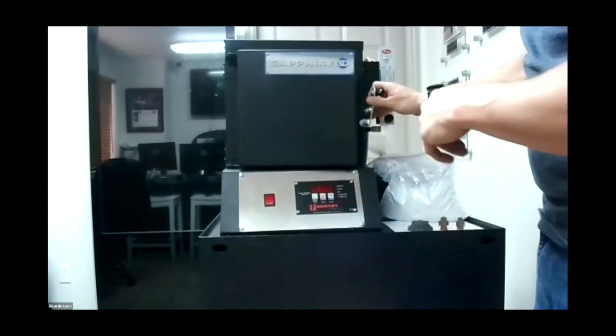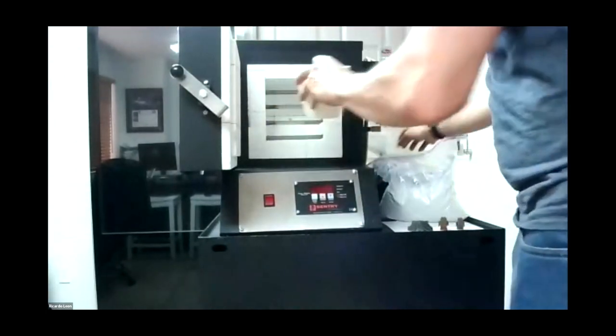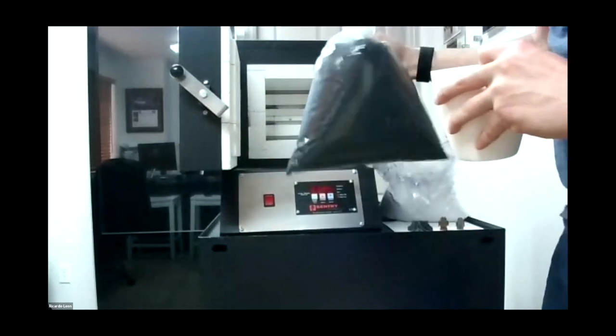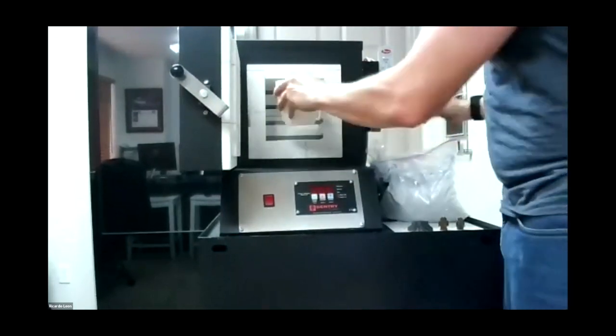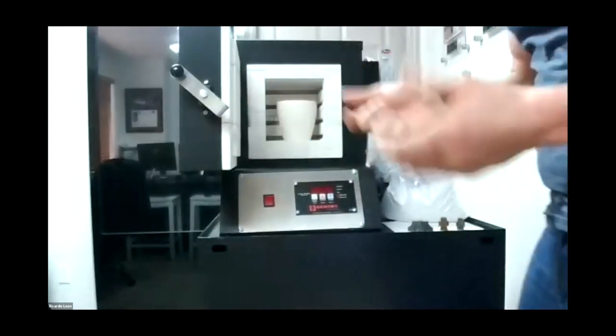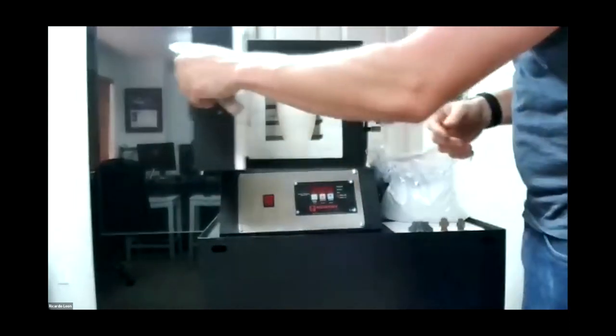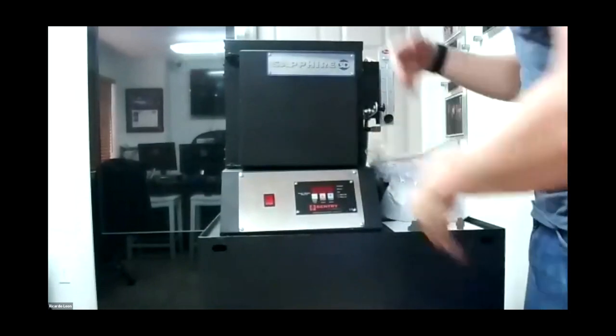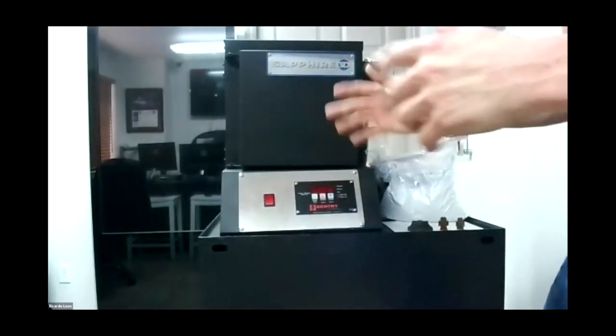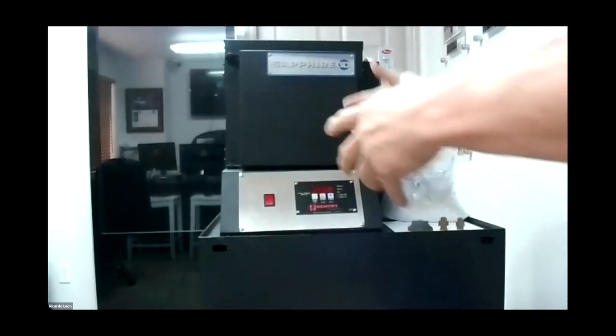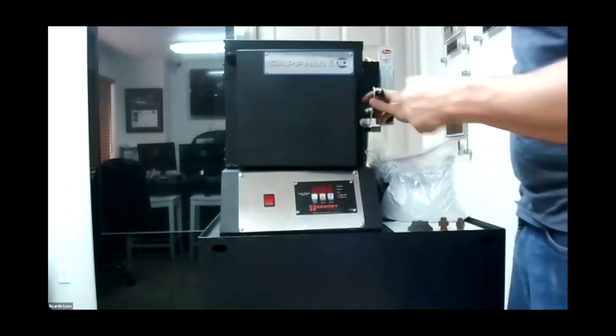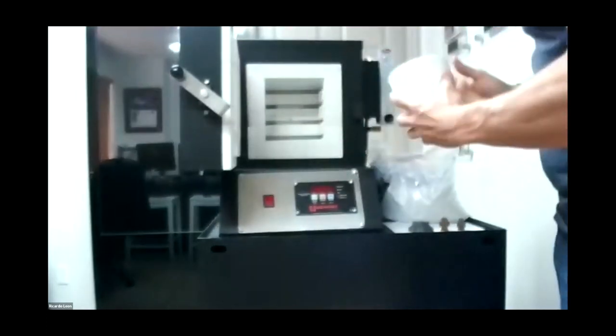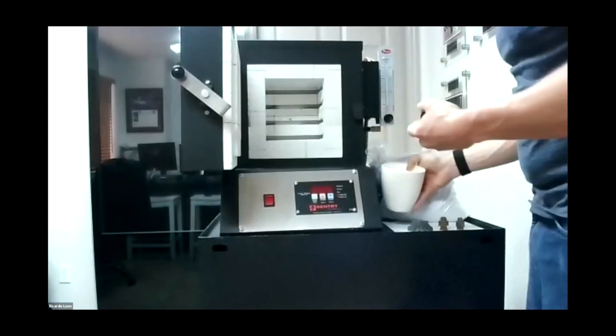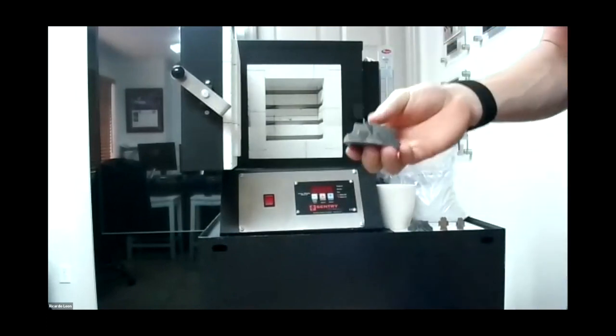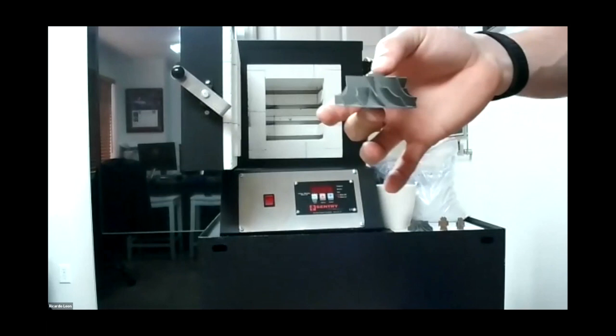Then once that process is done, you take it out, and then you add this carbon powder, which is to help you keep the oxygen away for the sintering process. So you put some carbon powder in there, you put your part back, and then you sinter it. And this part, depending on the material, takes between 5 to 8 hours for finishing. Once the part is done, you take it out, you remove it, and then you polish it as required, and then you have a true 100% metal part.